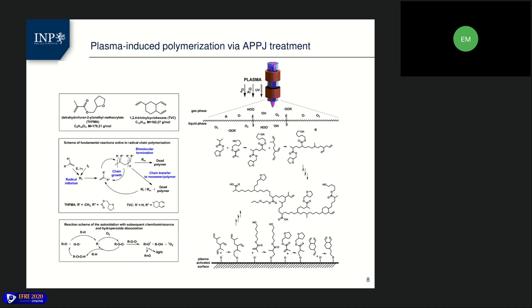Oxygen found in the bulk of TVC film was mostly in the form of ether and aldehydes, which can be caused by the action of alkoxy radicals that are known to be reactive towards carbon double bonds and are typically used as initiators of free radical polymerization.